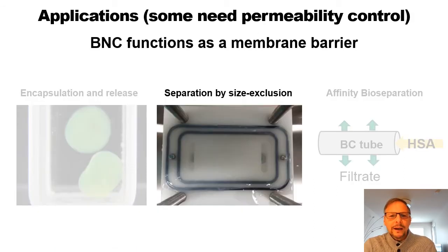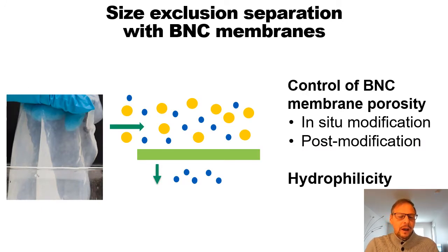Okay, let's very quickly look at another example of bacterial cellulose membranes that can be used for separation. In the example that I will show, we will refer to size exclusion separation. In other words, this has to do with filtration. We have on the left the wet pellicle of bacterial cellulose that can be used as a film for filtration. That's what you see in the center. We can produce membranes, in this case bacterial cellulose membranes that will look like what we have in the center in green. The porosity of those membranes can be controlled by modification during the growth of the cellulose or by post-modification. Also, the hydrophilicity and hydrophobicity of the membranes can be controlled. So it can be quite an opportunity for us to think about this type of size exclusion element.